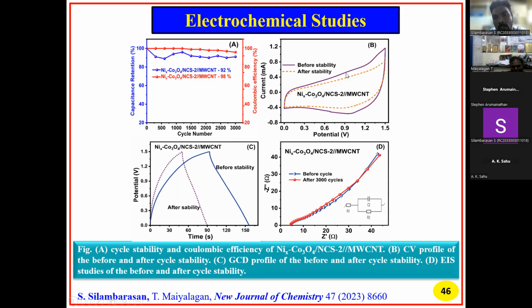Figure B is the before cycle stability and after cycle stability measured by CV. Before cycle stability, it measured around 0.9 in current. After stability, it is slightly decreasing. Like that, the charge discharge was also measured before and after cycle stability. Next one, for impedance spectroscopy, before cycling and after 3000 cycles, we measured the impedance spectroscopy.